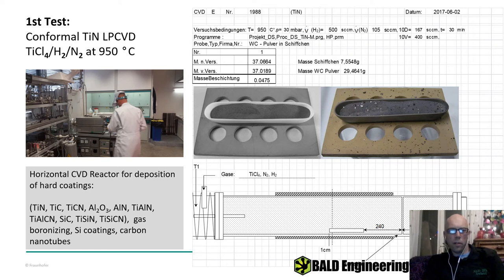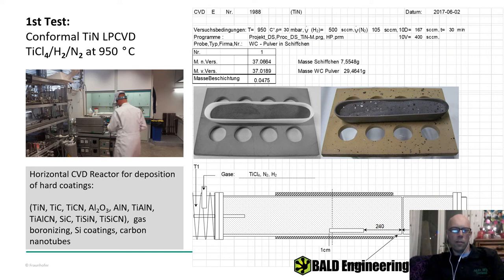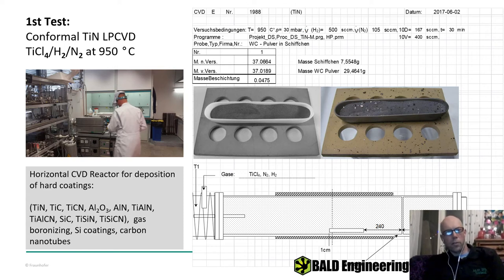This was the process our expert recommended for the best conformality. We really wanted to test whether we need to go through the hassle of ALD or whether CVD would suffice. As Mandy Høen said, the best conformality would be a TiCl₄-based process using hydrogen and nitrogen mixture instead of ammonia at 950°C, run for about half an hour in a horizontal furnace.